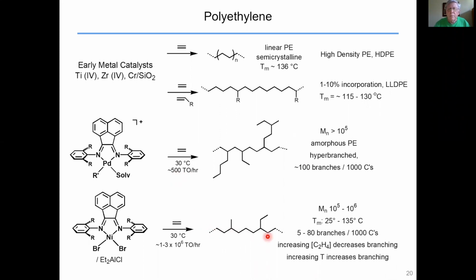And you get more lightly branched materials. The TMs can range from 25 to 135, depending on the branching. We can see 5 to 80 branches. And what we see is that if we increase the ethylene pressure, we decrease the branching. And if we increase the temperature, the branching increases. So we can control the extent of branching simply by temperature and pressure.